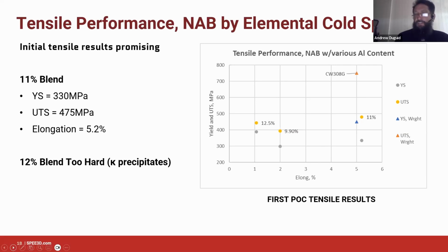And there's actually quite a lot that you can infer from a plot like this, if you sit down and think about what might be driving trends and so forth. And we do an awful lot of this at SPEE3D. So what I've done is I've put one of the wrought specifications on there for nickel aluminium bronze. That's the CW308G spec. And that's actually pretty good.